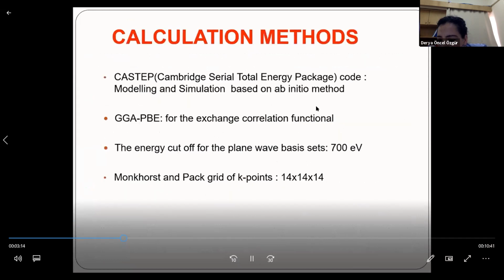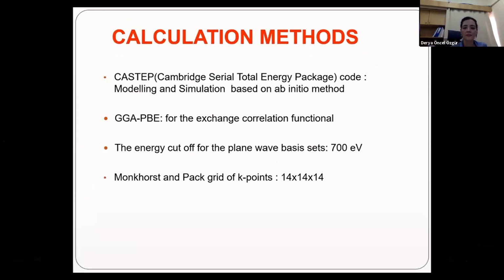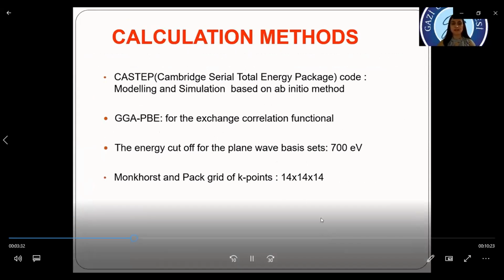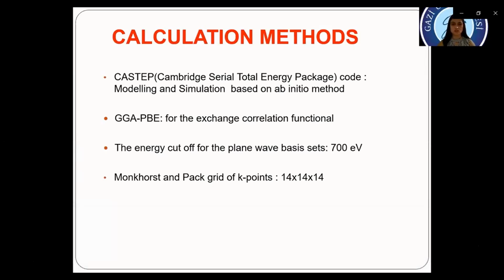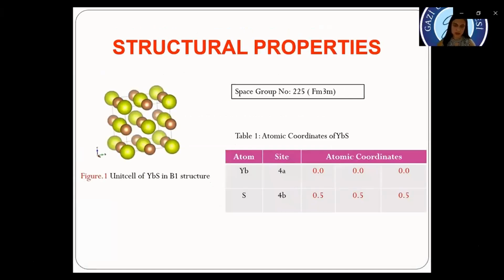Calculation methods. We use CASTEP code, modeling and simulation based on ab initio methods. GGA-PBE for the exchange correlation functional. The energy cutoff for the plane wave basis set is 700 eV. Monkhorst-Pack grid of k-points 14 by 14 by 14. Structural properties.